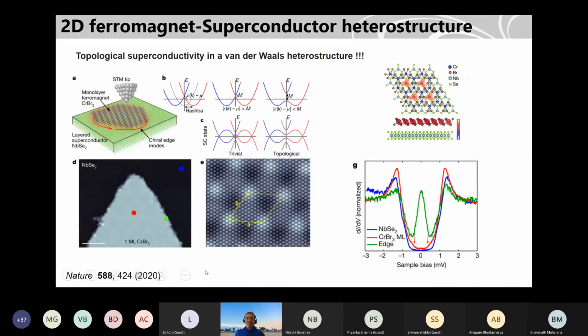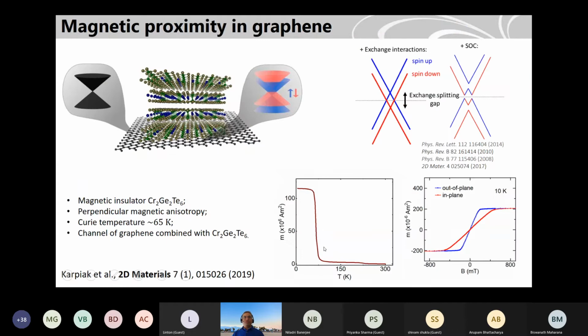And recently, just in December, one more paper came out showing that you can find topological superconductivity in van der Waals heterostructures. So it's niobium selenide, a superconductor, and then you have a monolayer of ferromagnet. And this is a scanning tunneling microscope experiment where they find these red, green, and blue data points. In the green one at the edges, they find the zero bias peak, and they attribute it to topological superconductivity, because due to proximity, you can make such things theoretically. So maybe further experiments will tell more about such systems.